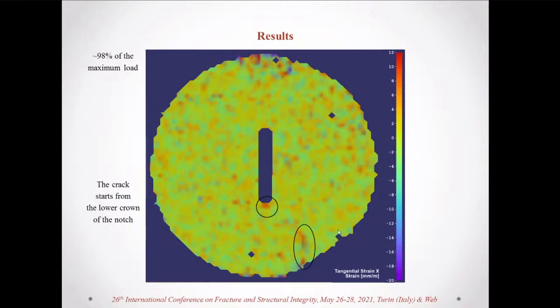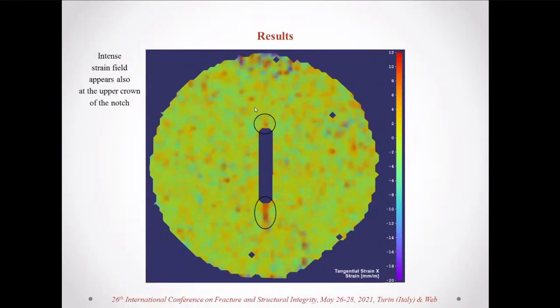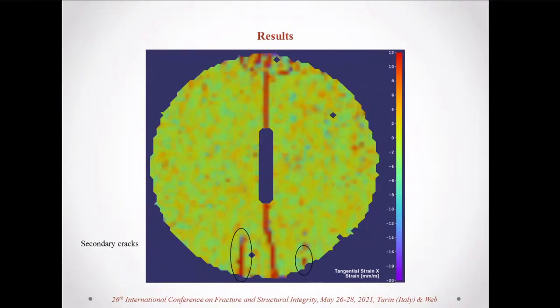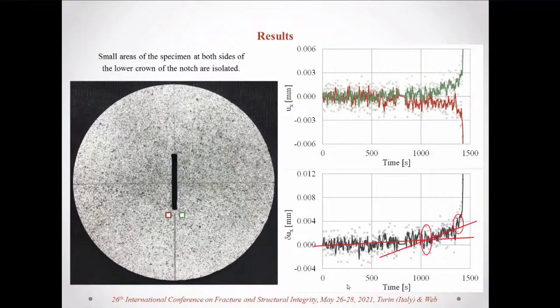And we studied the distribution of the strains along the horizontal axis developed on the disc. And it can be said that the crack starts from the lower crown of the notch, while a few seconds later, an intense strain field also appears at the upper crown of the notch. Both fields become longer and longer until the fracture of the specimen, while right afterwards, secondary cracks also appeared. But we always have in mind that the specific marble is extremely brittle, and we also have in mind that the cameras have a finite resolution. So, okay, we detected the point from which a crack started, but at which time instant?